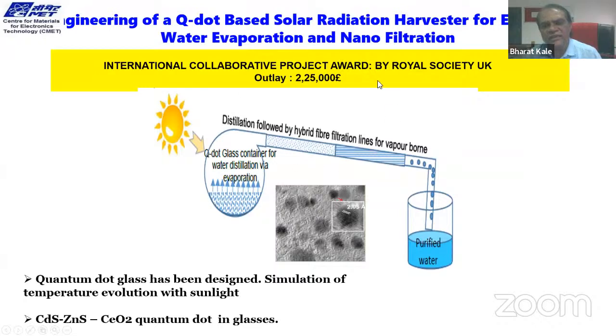So using the photocatalytic technique, we are exploring whether we can also purify water. Some of the glasses can be made quantum dot based, which can cover the whole spectrum from UV to almost near IR. They can absorb sunlight, and the energy can be transferred to the water so that the water can be boiled, filtered, and purified water can be possible in natural sunlight. We are very close to this now, and we are getting 80 degrees temperature with some of the quantum dots, and now we can see how we can coat the glass reactor.